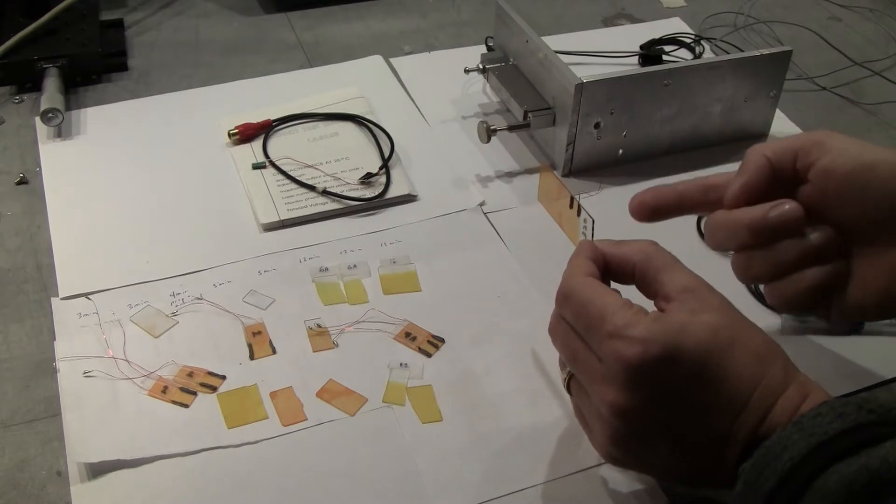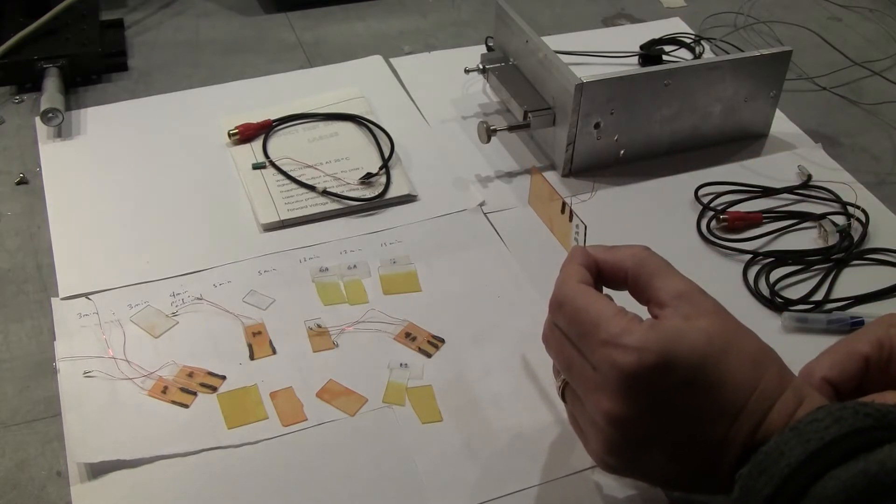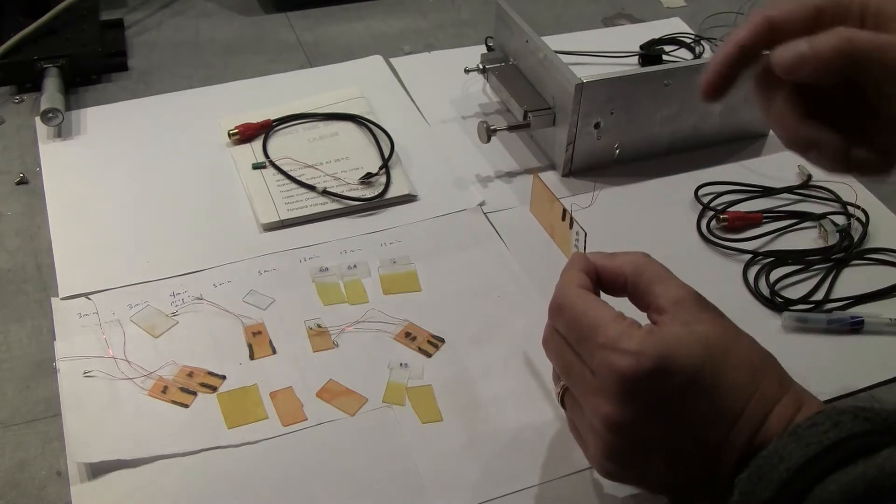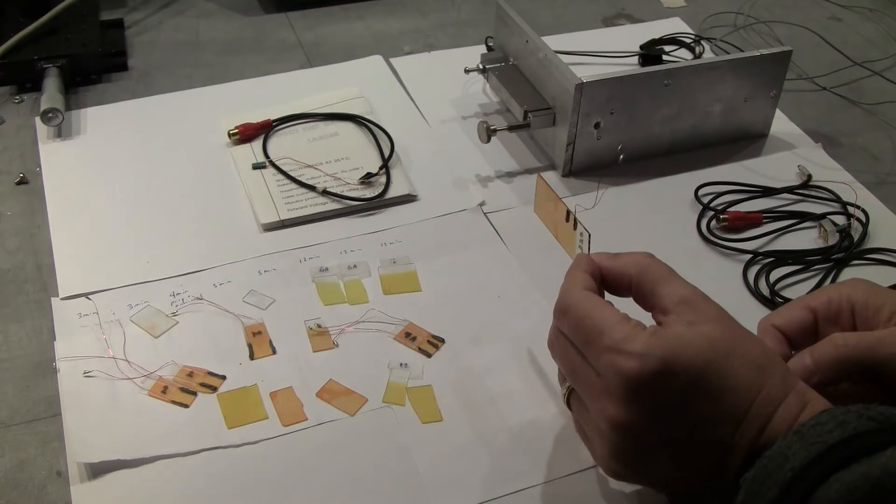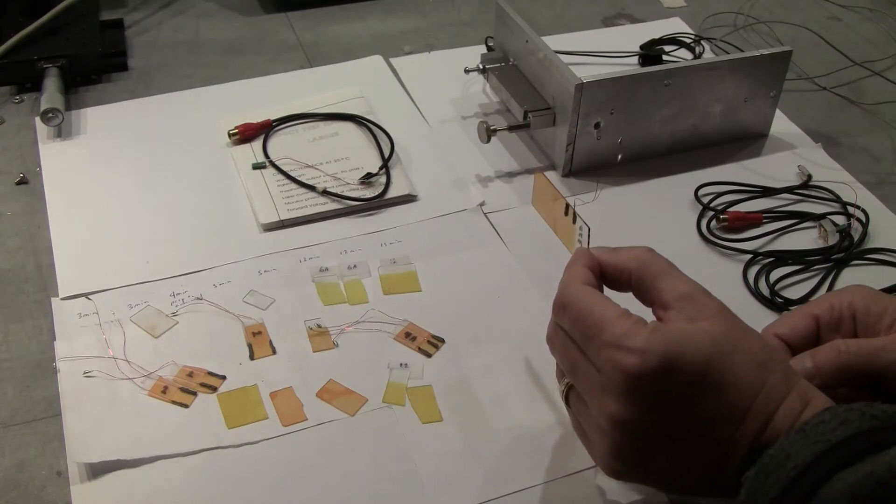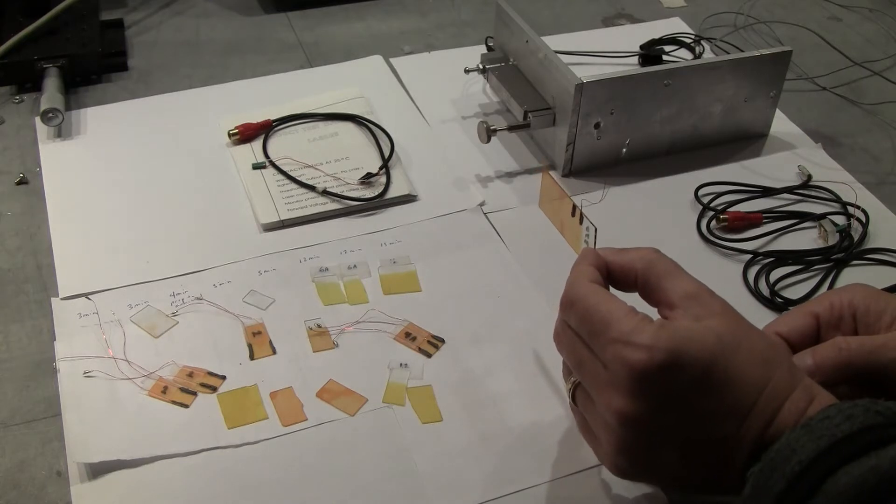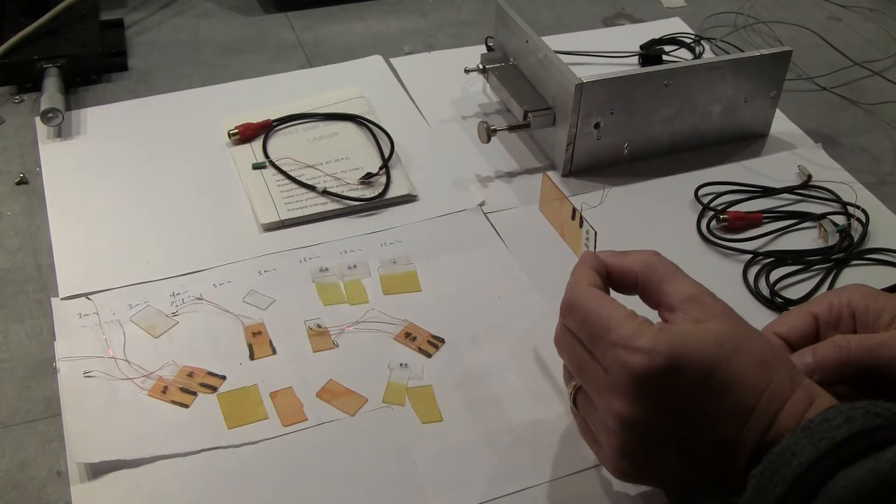What it requires is, firstly, that the sensor has to be transparent, and secondly, that the photo-detecting film has to be very, very thin, so that when the standing wave forms across the film, the film thickness is thinner than the wavelength that you're trying to measure. That's usually on the order of maybe 50 to 100 nanometers, something like that.